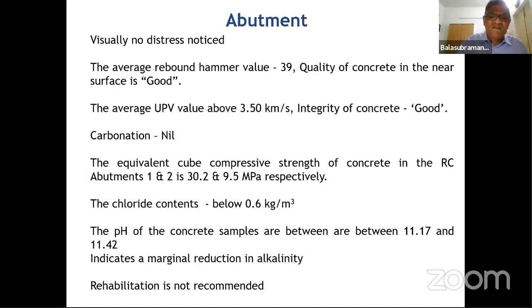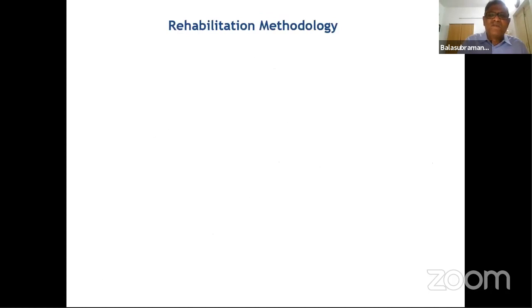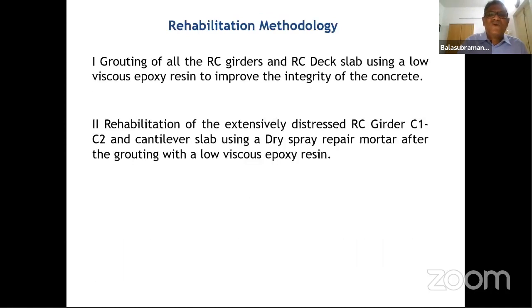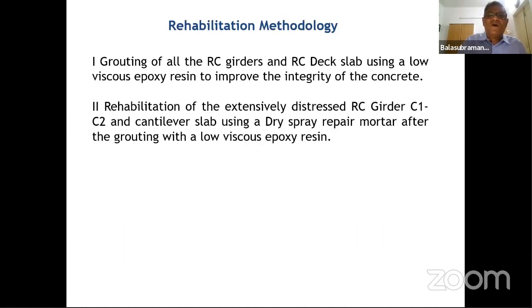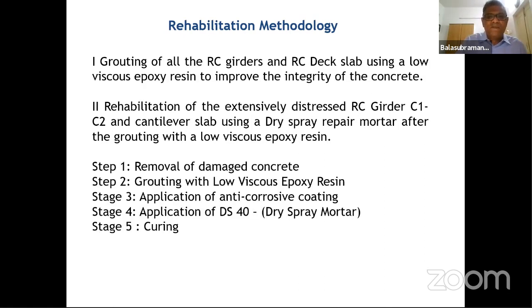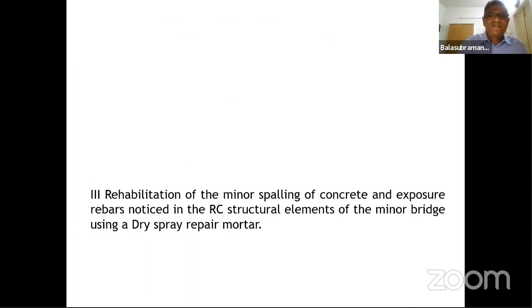So the abutment was perfectly all right, so no rehabilitation methodology was given. The final rehabilitation methodology was grouting all the RC girders and deck slab using a low viscous epoxy resin because they were in bad shape. There was only one girder which was extensively distressed, for which we recommended dry spray mortar. The general methodology is removal of the damaged concrete, grout, then anti-corrosive coating, and then apply the dry spray mortar, or the polymer modified mortar in some cases, or microconcrete jacketing in some cases, and curing. I'll just stop with that.